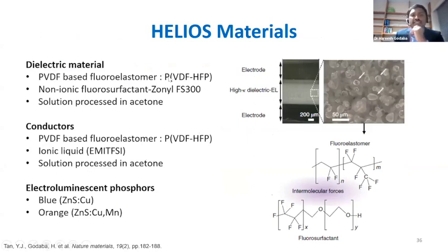Yeah, so here are the various parts, or materials, that go into making this Helios device. First we need a dielectric material. So we use this PVDF based fluoroelastomer, which is called PVDF HFP. And then we mixed in this non-ionic fluorosurfactant called Zonyl FS300. What this does is it makes the polymer chains a bit mobile, which actually helps in self-healing. So when we cut it, the mobile polymer chains can help it to self-heal. So basically, this is the material that makes this device self-healing. And both of these together are solution processed in acetone.